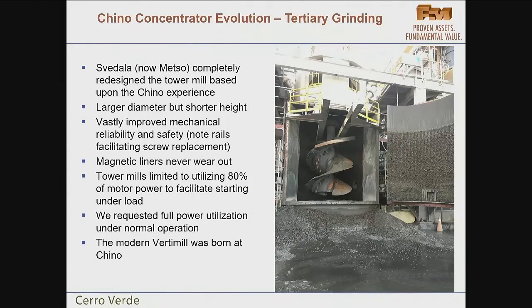So to their credit, Svedala, now Metso, took these learnings and they completely redesigned the tower mill based upon the Chino experience. You see a Verti mill on the right-hand side: large diameter, short height, magnetic liners on the door, never wear out. One characteristic of the tower mills was we were limited to 80% of motor nameplate so they could start the thing if it stopped.